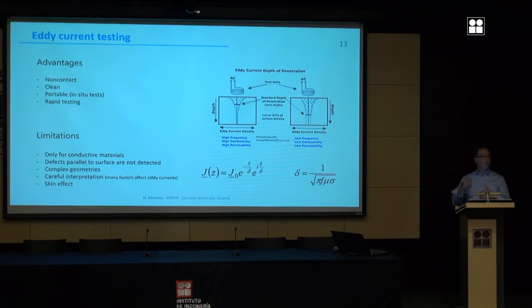A defect that does not affect the eddy current flow will not be detected. Flaws that are parallel to the surface will not affect eddy currents, since the eddy currents are parallel to the flaw, so they will not be detected. Complex geometries like edges or corners are difficult to characterize. A careful interpretation is necessary, since many parameters affect eddy current, in particular the liftoff. A little variation of the liftoff will give you a completely different variation of the impedance.